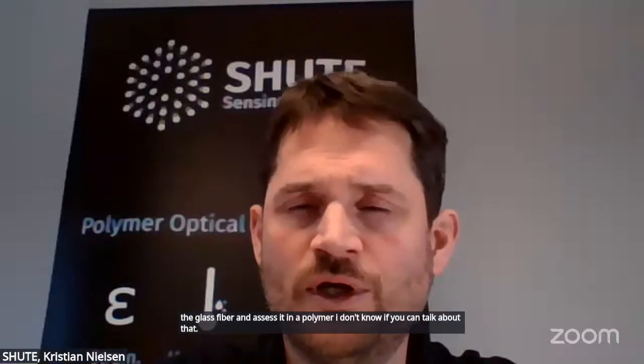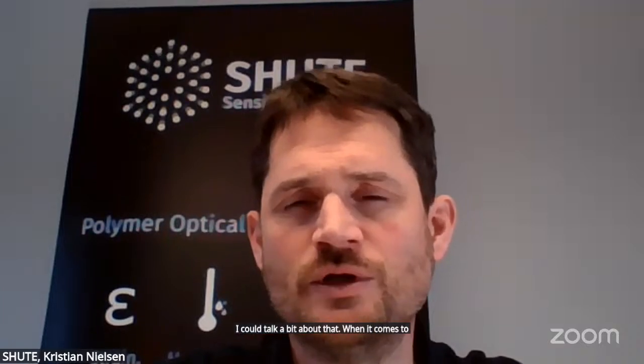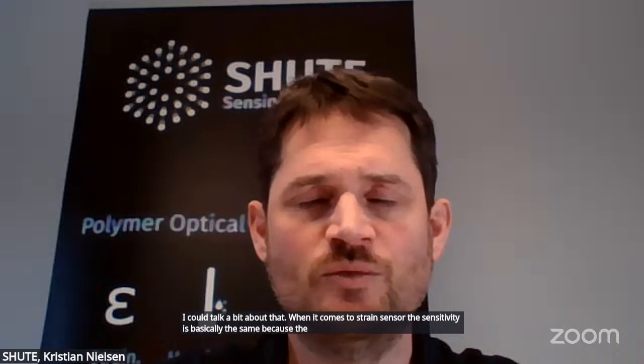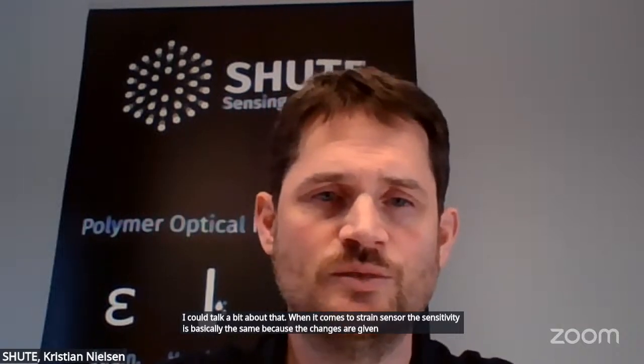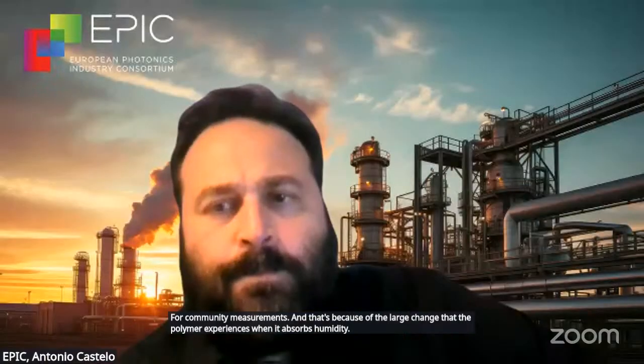I could talk a bit about that. When it comes to strain sensor, the sensitivity is basically the same because the changes are given by mechanics. So basically, a polymer fiber and a glass fiber, they change the same. For humidity, the sensitivity is about 20 times higher than currently available glass fibers for humidity measurements. And that's because of the large change that the polymer experiences when it absorbs humidity. Okay. Yeah, and the temperature sensitivity is slightly higher for polymer as well, but the range is much more limited compared to glass.